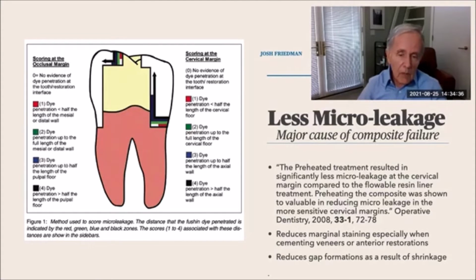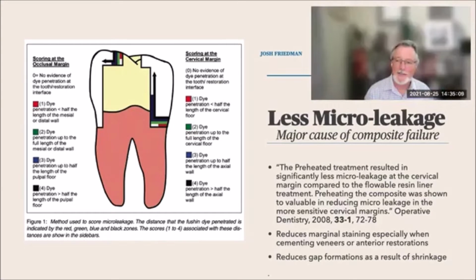Well, as we said before, when you use a flowable, you're using it to get adaptation, but what we know about flowables is that they're less heavily filled and they're going to shrink more. In the case of a warm composite, it doesn't turn it completely into a flowable, but it becomes much more flowable-like. And at the same time, it certainly doesn't shrink as much as a flowable. So that gives us the best possible use of the composite, and also eliminates another product that you have to keep in the office. That sounds good, Josh. Thanks.